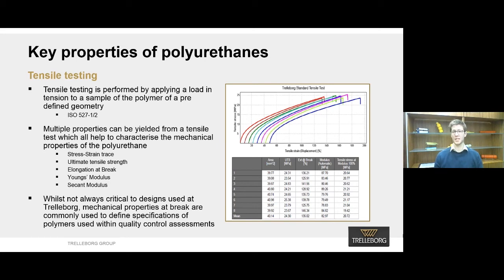We perform this test across multiple temperatures to fully characterise the material. It's a critical aspect for designs, but it's also a common test as part of QC methodology to validate the high quality of all the parts that Trelleborg produces. We test on dog bone samples which we stamp out from plaques of the polymer, or we machine these test samples from cast parts, which highlights the properties in a finished part as well as a small sample.